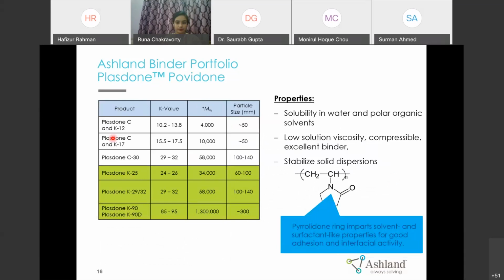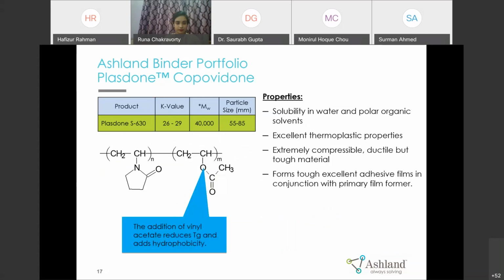Then we have Povidone, which comes with the brand name of Plasdone. We have K25, K29/32, and K90, which vary in molecular weight and viscosity. This is an excellent polymer for water soluble APIs. Then we have Plasdone S630, which is also known as Copovidone. Here you can see there is an additional vinyl acetate substitution, which reduces the Tg, the glass transition temperature, and adds hydrophobicity to the polymer. Like povidone, copovidone works very well with water soluble APIs, and it is also recommended for dry granulation or direct compression.